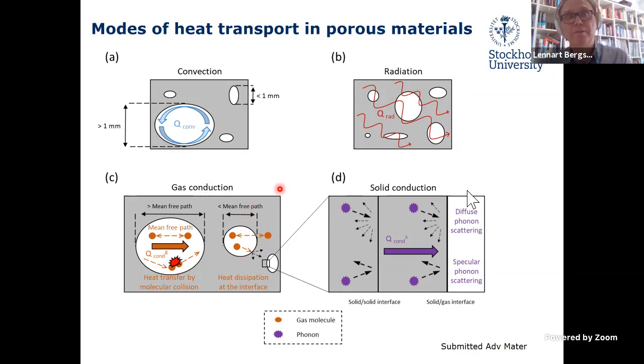When it comes to gas conduction, the main issue is the mean free path of air. So if you can start to reduce the pore size below the mean free path of air, you can have the so-called Knudsen effects, and that means you will have a reduction of the gas conduction contribution.